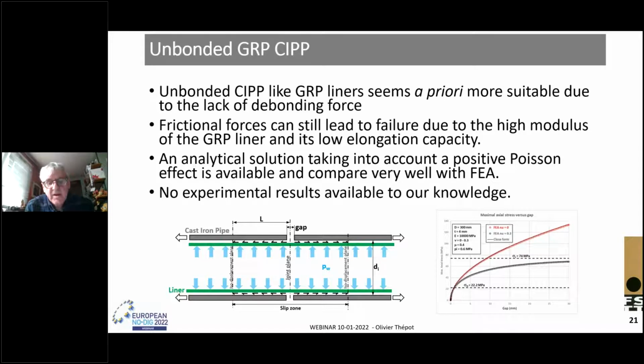However, frictional forces can still lead to failure due to the high modulus of the GRP liners, typically 10 to 20 times higher than the modulus of the woven polyester liner, and its low elongation capacity.